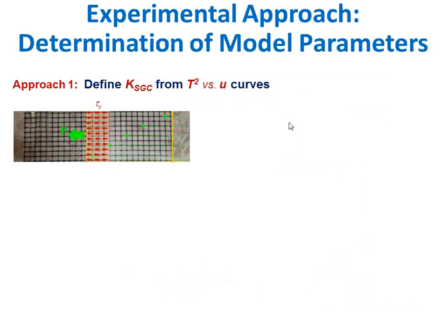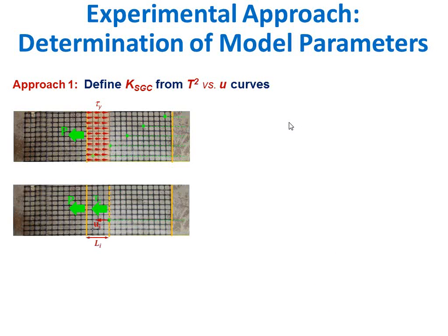And this is essentially, if we get that curve, what we would like to get. One possibility would be if we plot the tension versus the displacements at different times, and we plot tension squared versus displacement, and we get a straight line, then we're happy. If we don't get a straight line, we need to go back to the drawing board. So essentially, we would be happy if we get something like this, but even more.